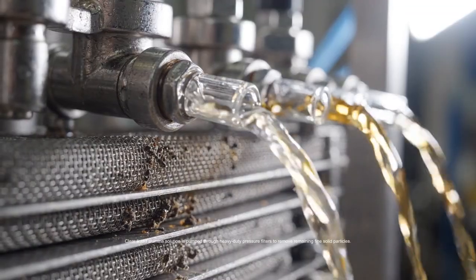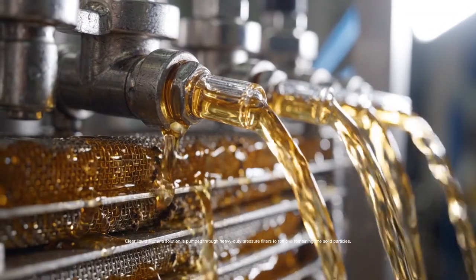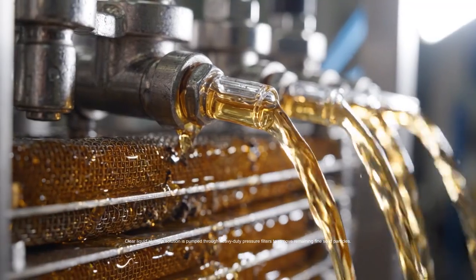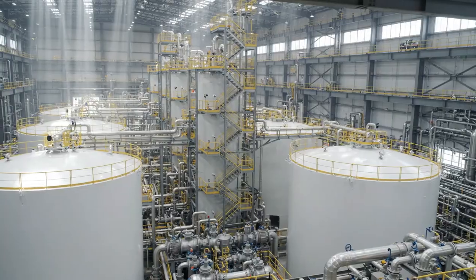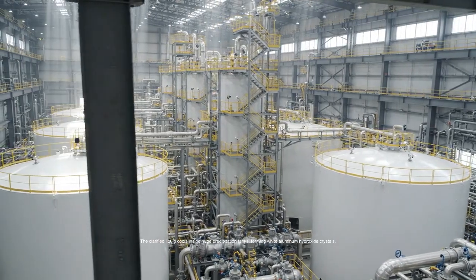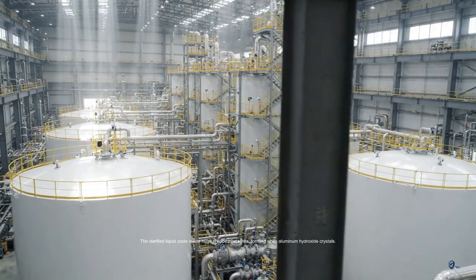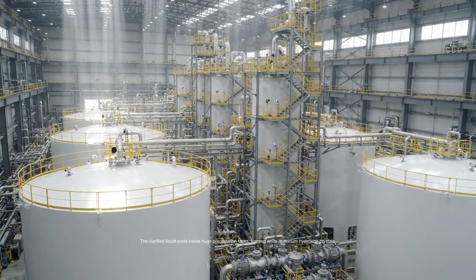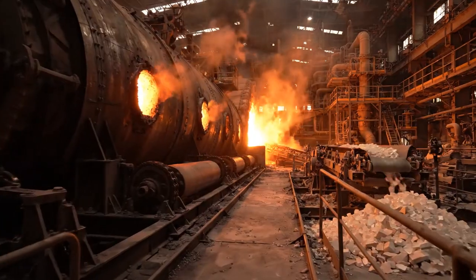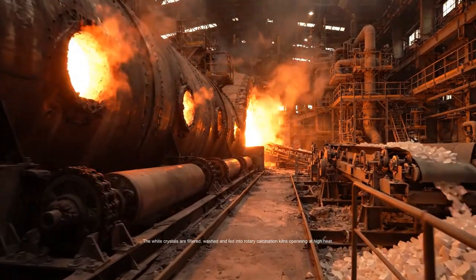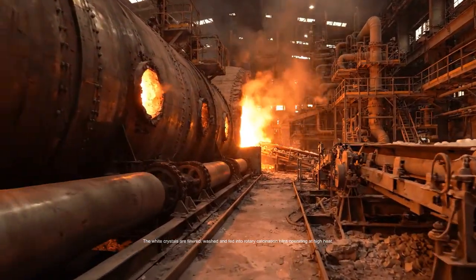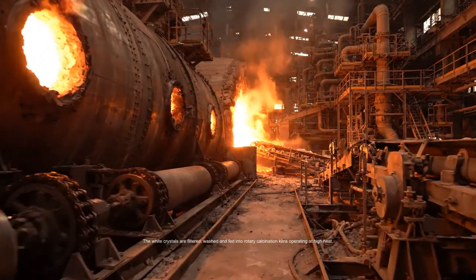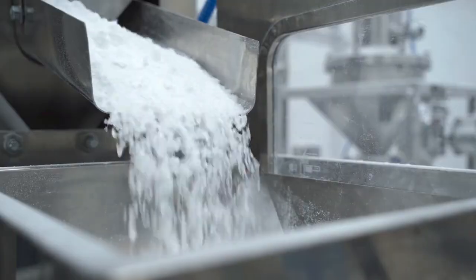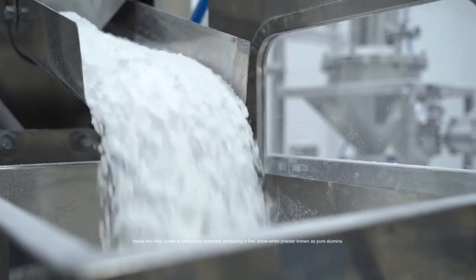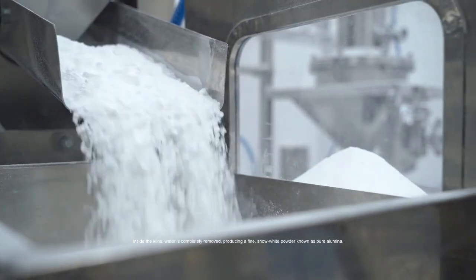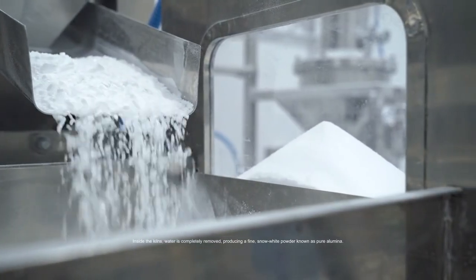Clear liquid alumina solution is pumped through heavy-duty pressure filters to remove remaining fine solid particles. The clarified liquid cools inside huge precipitation tanks, forming white aluminum hydroxide crystals. The white crystals are filtered, washed, and fed into rotary calcination kilns operating at high heat. Inside the kilns, water is completely removed, producing a fine snow-white powder known as pure alumina.